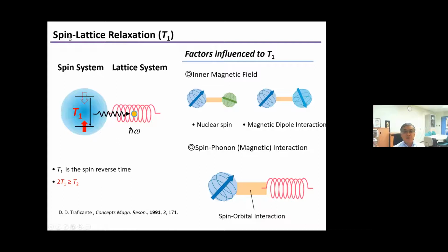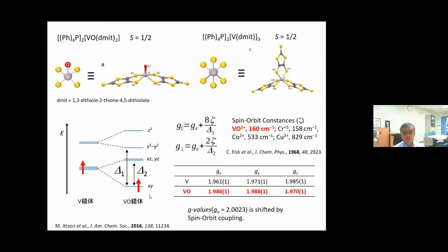And also the spin-lattice relaxation time T1. The factors inversely related to T1 are the internal magnetic field and the spin-phonon interaction. The most typical one is the oxo-vanadium compound. Spin is S equal 1/2. So this is the material here.